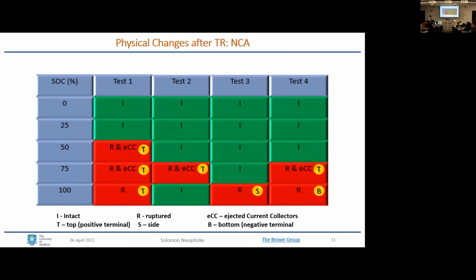Then we look at the physical changes that happened to the battery after the test. Like I said earlier on, the test was repeated 4 times for each state of charge. You can see for 0 state of charge, we have this line of number of tests, 1, 2, 3, 4. The green box represents where the battery remained intact after the test, while the red boxes represent where the battery ruptured during thermal runaway. The orange circle represents the part of the battery where the rupture occurred. T stands for the top, B for the bottom, and S for the side.